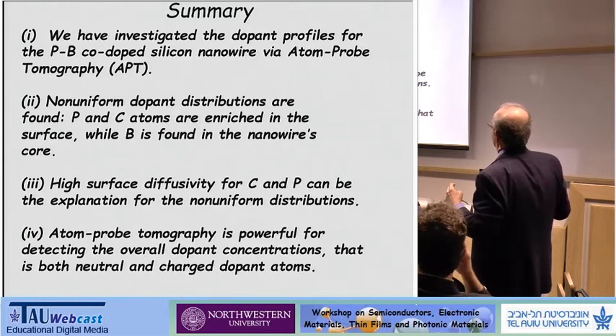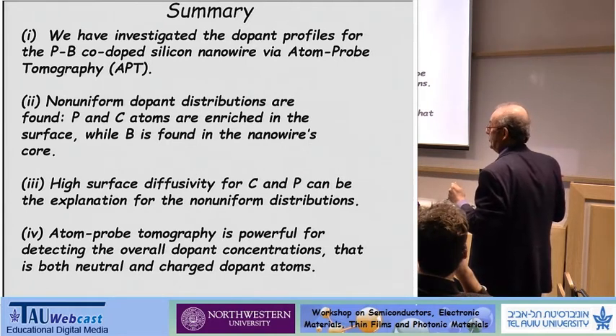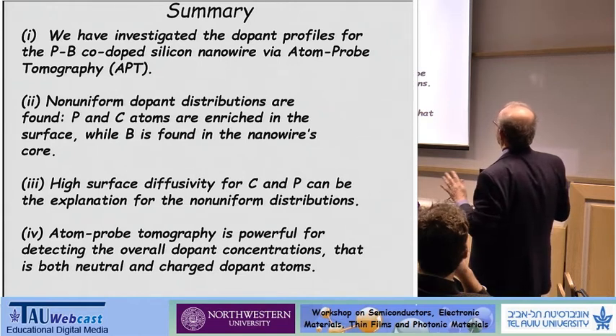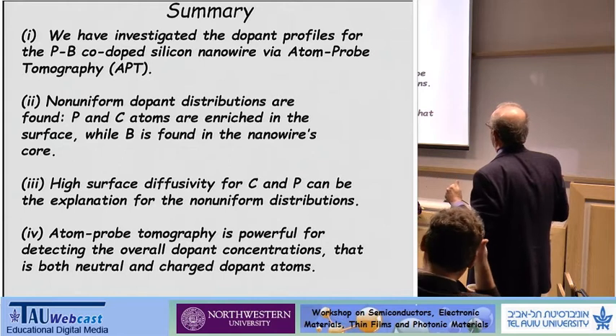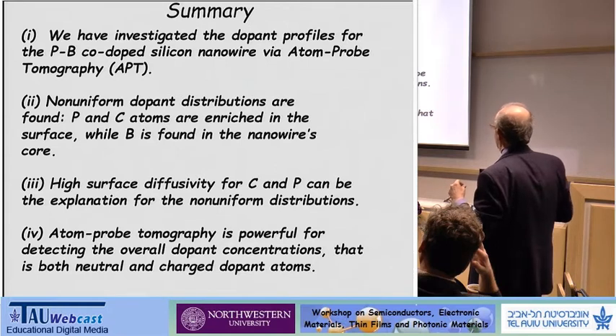Okay, so what have we done here? In summary, we've investigated these dopant profiles for phosphorus and boron. Originally, Mr. Sun had written this BP, which I said is beyond petroleum, BP. Okay, so these are co-doped, and they were analyzed by atom probe tomography. And the phosphorus and the carbon atoms are enriched in the surface at the interfaces. Boron is found more or less uniformly distributed in the core of the nanowire. And you can explain this because both carbon and phosphorus have high surface diffusivities. They're preferentially segregated at interfaces. And this is what gives rise to this non-uniform distribution.